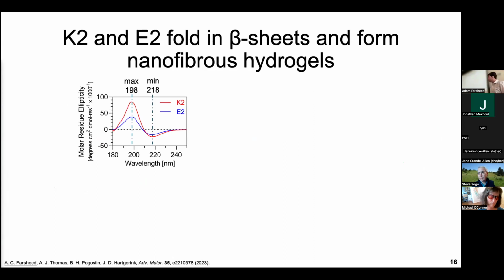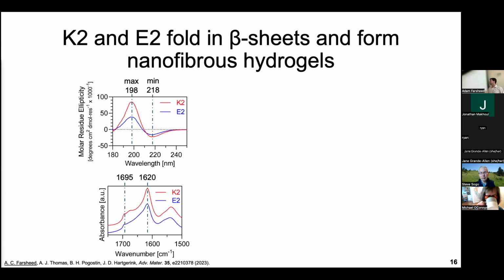And so before we jump into the fancy 3D printing stuff, we need to do some basic chemical characterization of these materials. And what I'm showing here is circular dichroism, where we can get an understanding of the secondary structure that these materials form, and the maxima at 198 and minima at 218 for both the K2 and E2 MDP show that we are getting a beta sheet secondary structure, as we have seen in the past and would expect. And we can also do FTIR here to confirm that analysis. So again, we're getting these beta sheets starting to form.